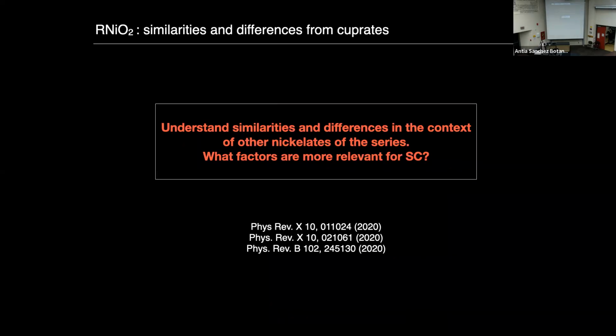So all in all, these infinite layer nickelates seem to have quite a few similarities with the cuprates, but also important differences, in particular, this larger charge transfer energy, or lower PD hybridization if you prefer, and the involvement of rare earth D states. But what we wanted to understand, rather than focusing too much on the infinite layer compound, which we actually did, was how all of these differences and similarities fit in the context of other layered nickelates of the family, because what we were thinking about was trying to establish a whole family of superconductors, again, rather than just a single superconducting material.